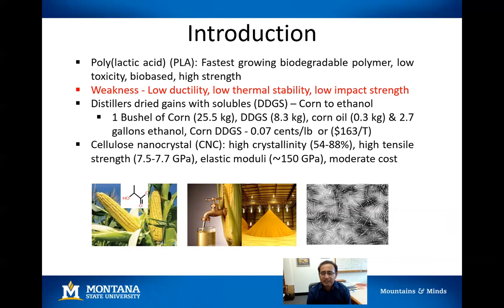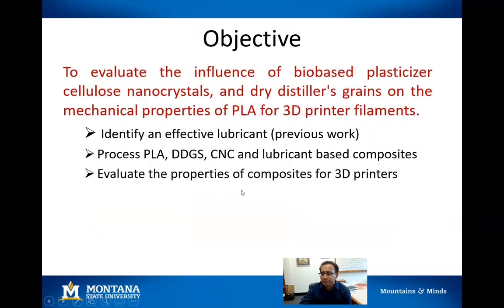The second material, distillers dried grains with solubles, is a byproduct of corn to ethanol production. A bushel that is around 25.5 kg gives around 8.3 kilograms of DDGS and 2.7 gallons of ethanol. And the current price of DDGS is around 7 cents per pound. So it's a fairly cheap material. And cellulose nanocrystals derived from cellulose are highly crystalline, have high tensile strength and elastic moduli, and they have a moderate cost.